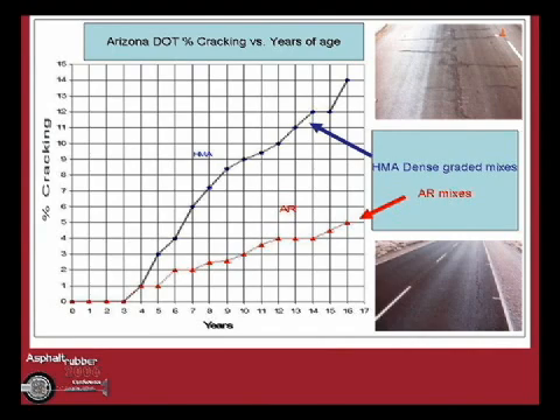Cracking experience in Arizona. This is why this material has really been so widely used in Arizona, because it does reduce the cracking. As you can see, over a long period of time, you get up to about 10% cracking after about 10 or 12 years. Now the road's in pretty poor shape, whereas if you use asphalt rubber, even out here at 17 years, it's still very small amounts of cracking. You don't see much in the way of fatigue cracking. You do see some.